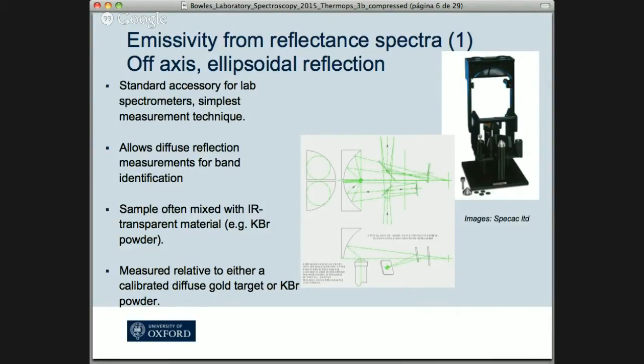It's essentially two ellipsoidal reflectors and a bunch of mirrors that spread the beam from the spectrometer out in the sample compartment of the spectrometer, so it hits the sample cup at a grazing angle. Then ellipsoidal reflectors collect the light and pass it into the detector module, which picks up the interferogram. So the light comes in, gets splayed over the sample, diffusely reflected, picked up by the ellipsoidal reflectors, and then shoved onto the detector to record the interferogram.